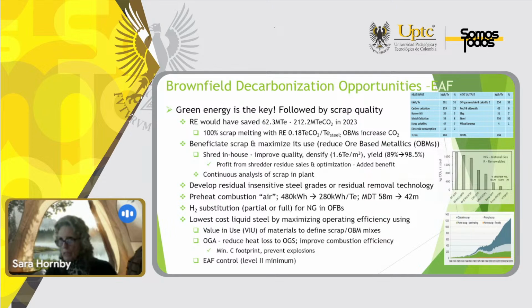And if we shred the scrap in-house by our own scrap shredder, we can improve the quality, the density, and increase the yield because you're cleaning the scrap, basically. And it's been seen that you can increase the yield from 89 to 98.5%. There's also the profit from selling the shredder fluff, as they call it, which is the non-ferrous that comes from shredding. Also need to have continuous analysis in the scrap plant to make sure of the quality of scrap that's going in the furnace. We need to develop residual insensitive steel grades or find a way of removing the residuals from the continuously recycled scrap.